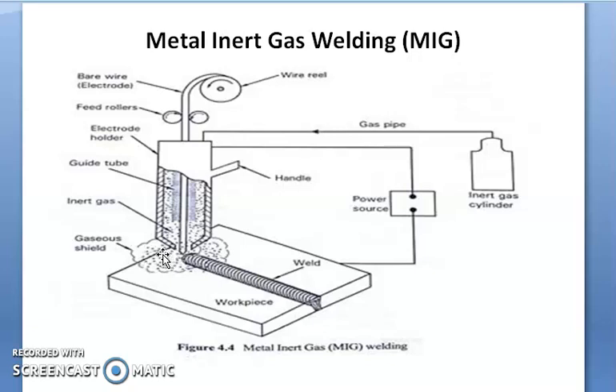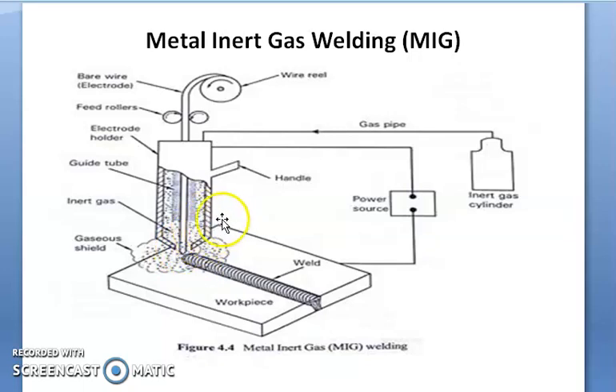When the switch is on, the welding torch is moved nearer to the workpiece. An arc is struck by touching the tip of the electrode to the workpiece. When the electrode is separated a small distance of 1.5 to 3 mm, the arc still remains between the electrode and the workpiece. The high intensity of the arc melts the workpiece metal, forming a small molten pool. At the same time the tip of the electrode also melts and combines with the molten metal of the workpiece, thereby filling the gap between the two workpieces.